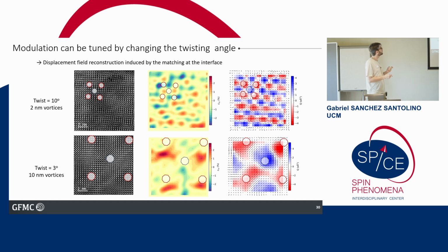So, for example, here we have vortices of around 2 nanometers, or 2.3. If we do a lower twisting angle, we are going to have larger vortices of around 10 nanometers. In comparison with the experiments that the community was doing before, where they have to carefully choose the thickness of the layers and the materials in the layers, so the sizes of these ferroelectric structures were fixed by the thickness of the layers, in this way we can create different strain landscapes with different periodicity, and then create these polar vortices with different sizes.